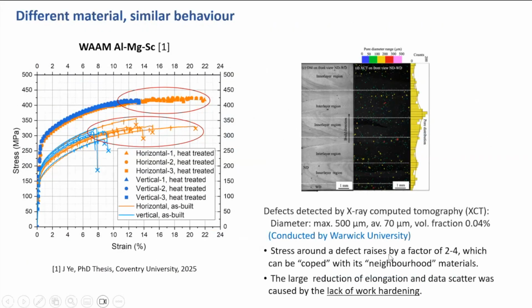Stress around the defects will raise by a factor of 2 or 4, so that can be coped by neighboring materials. They all work together to reach the yield strength. But the defects will reduce elongation because there's no work hardening. Most aerospace materials really lack post-yield work hardening, so the elongation will suffer.